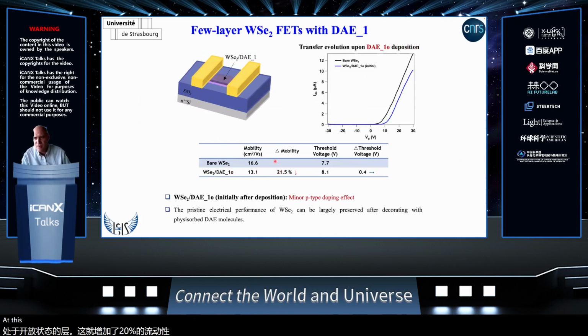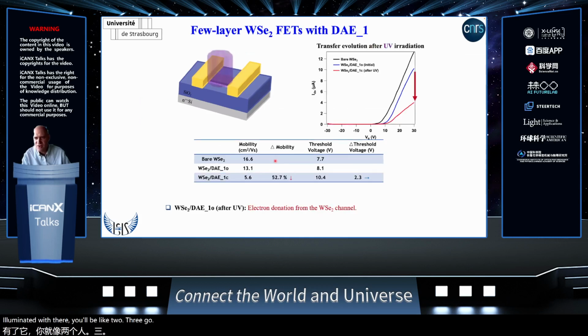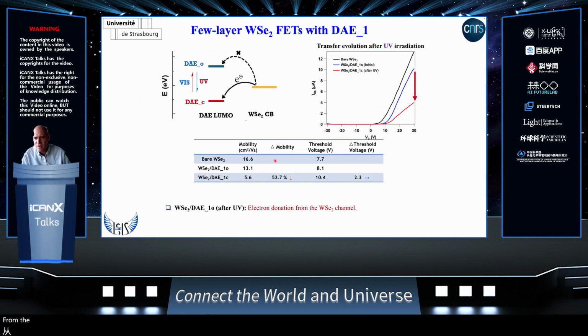At this point, we have illuminated with UV light to trigger the isomerization from the open to the closed state, and therefore we are creating traps. We are creating traps, and this is such that the electron mobility of the tungsten diselenide decreases by 50%. And you can see there is also a mild increase of the threshold voltage.